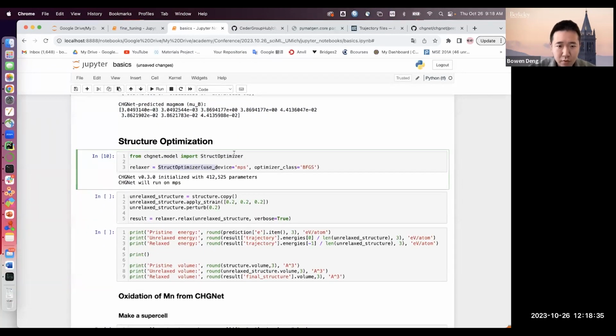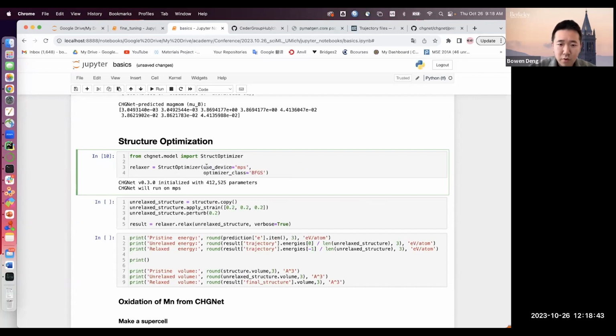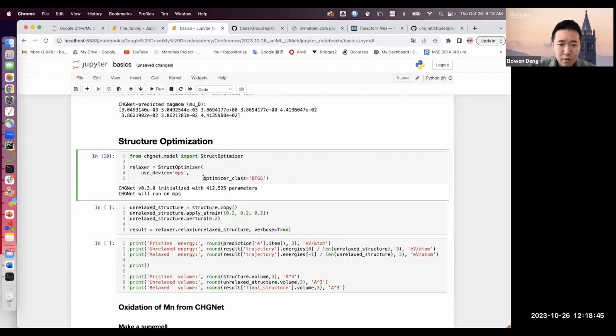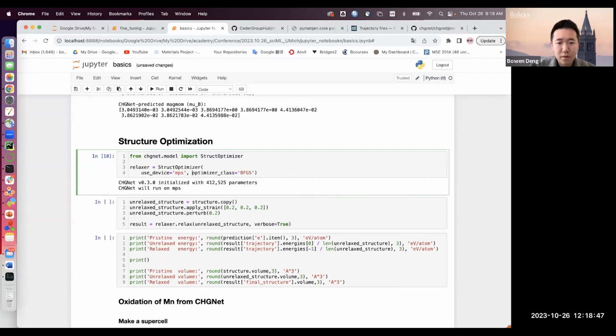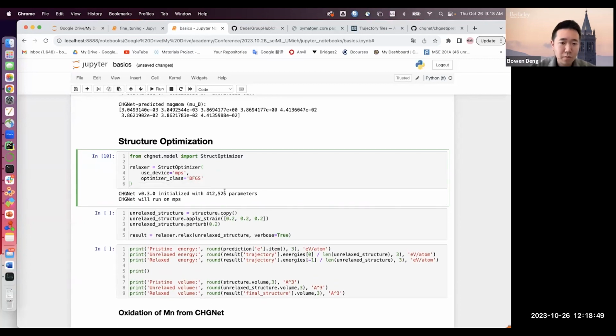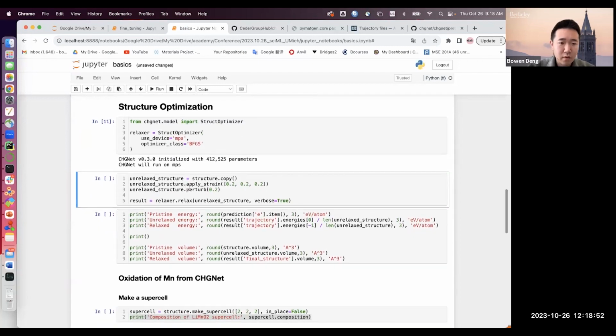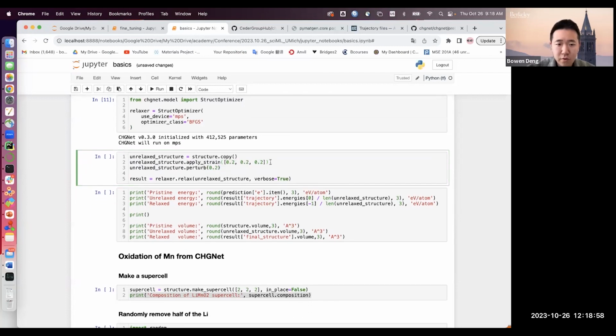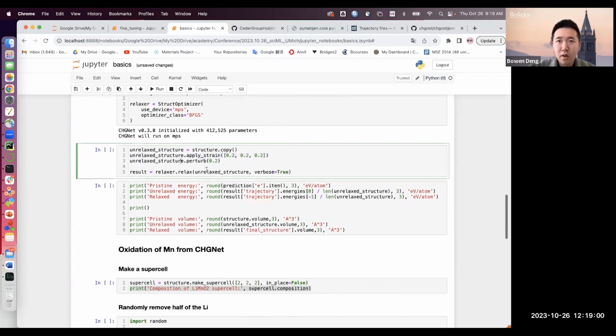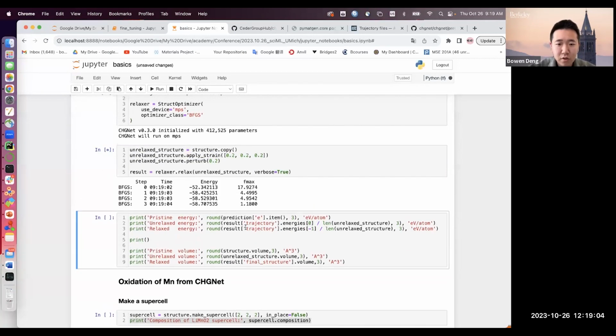Here we initialize a relaxer object, which is loaded from chgnet.model. And here we set use_device equals MPS again, and the optimizer we use is BFGS, which is a second order optimizer. We want to perturb this structure a little bit, right? So we apply a 0.2, 0.2, 0.2 strain to it, and we perturb the atoms a little bit, and we see if CHGNet can relax back the initial structure.